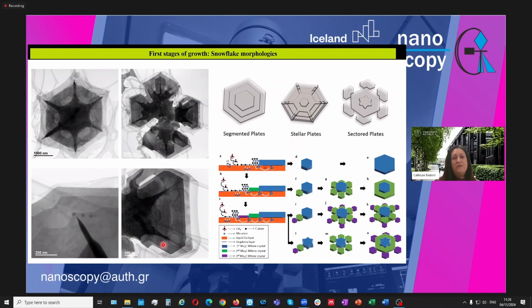Of course, the vertical growth happens in a slower way because the height itself poses a bulk diffusion barrier for molybdenum that prefers to move towards the edges. And so the lateral growth mode is faster than the vertical one.